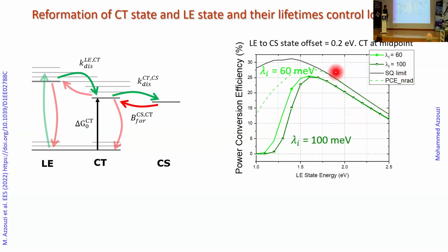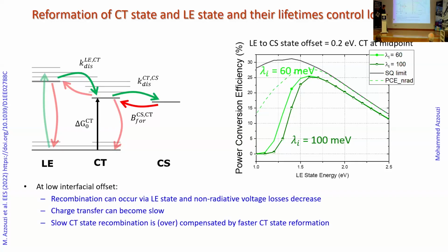The comparison here, so this black curve here is what you would have in the absolute radiative limit. And these green lines are the projection for the molecular materials. And we see that the projection crashes at low band gap. And that is because when the band gap becomes small, we start to squeeze the driving force that we can have to separate the charges, and we start to feed the excitations back into the CT state, back into the local excited state, and the excitations go to ground. So it's reflecting that competition that influences the behavior of the devices in real life.